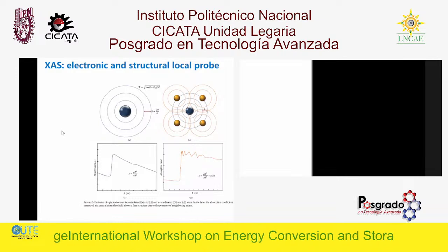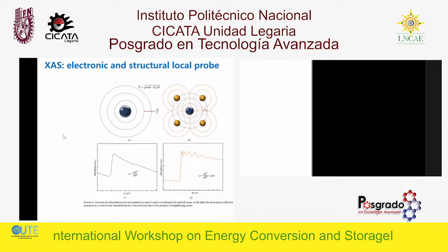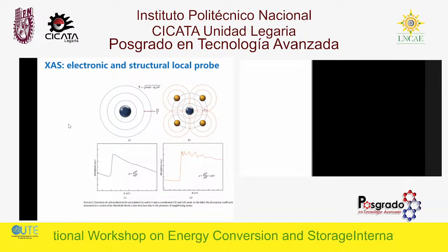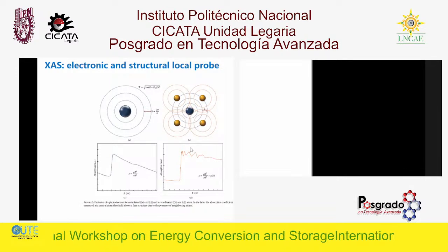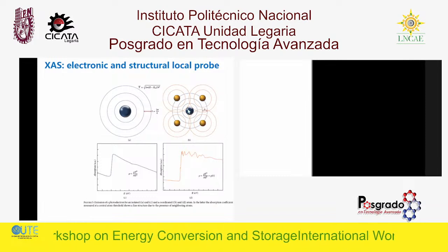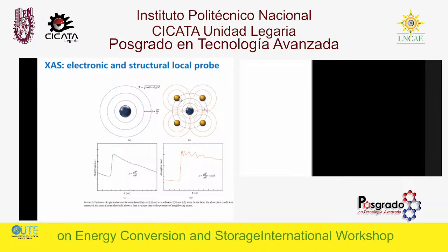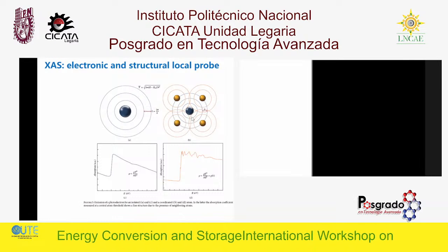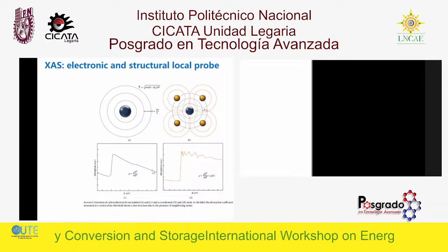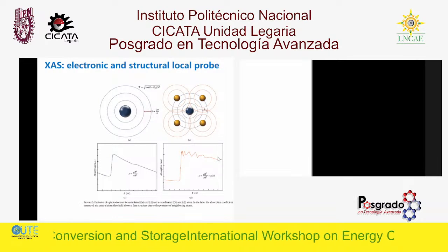Okay. And just to try to convince you that the oscillations are related to the presence of coordinated atoms, one of the characteristics of the spectrum is those oscillations, and they are present only in the case of coordinated atoms. So if this is the atom where you're going to create the core hole, these are the waves of the photoelectrons. You can see that photoelectrons can go out of the atom, then have an interference with some atoms that are just behind, and this produces information in the oscillations that you're going to measure here. If you have just a single atom, as in this one, you have just a monotonic decrease of the mass absorption coefficient with energy, without oscillations. So that's the experimental proof that oscillations happen only with coordinated atoms.